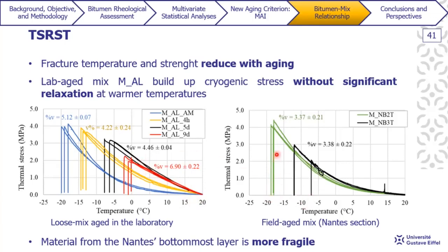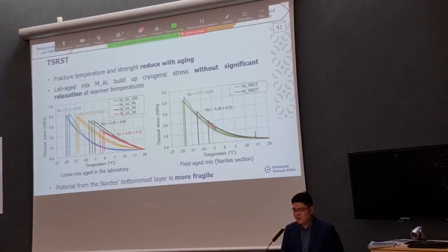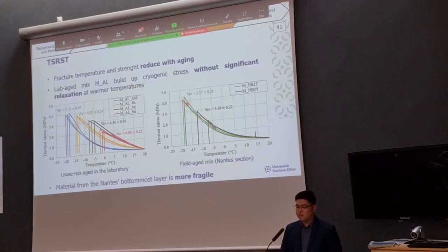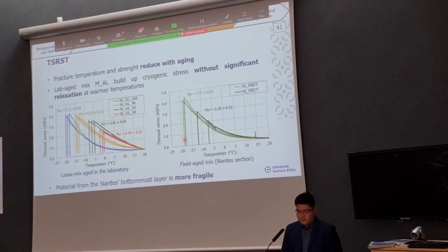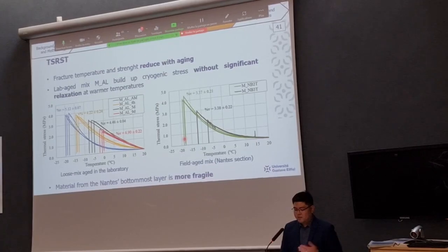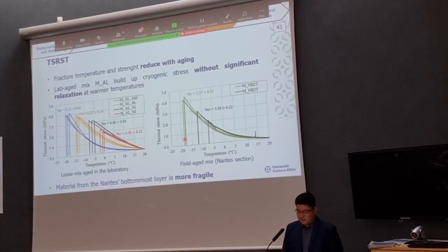And here we have the two curves representing the two materials from the Nantes section. The green curve represents the mixture from the intermediate layer, whereas the black one represents the asphalt mix from the bottommost part. So again, here we can see that the asphalt mix from the bottommost layer cracked at warmer temperature than the one that was taken from the intermediate course, which again seems to be that the material from the bottommost layer is more fragile, which is in accordance with what we observed with the bitumen.